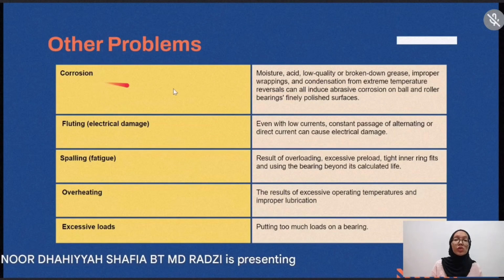Corrosion happens due to moisture, acid, low quality grease, and condensation from extreme temperature reversals. Fluting or electrical damage happens due to constant passage of alternating or direct current. Spalling or fatigue is the result of overloading, excessive preload, and using bearings longer than their calculated life. Overheating is the result of excessive operating temperature and insufficient lubrication. Lastly, excessive load occurs due to too much load applied on the bearings.